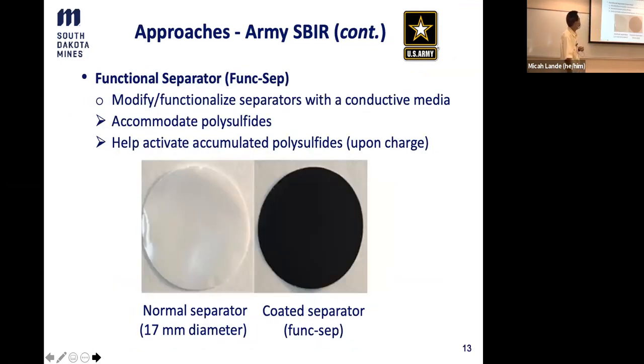And then another approach we use is the separator. We modify the separator with a conductive medium. Here on the left is the pristine, the normal separator, and it's polymer. And then the coated one, we call it a functional separator. So why do we do that? The reason is we try to accommodate the polysulfide in this functional separator, and also we help reactivate the accumulated polysulfide.